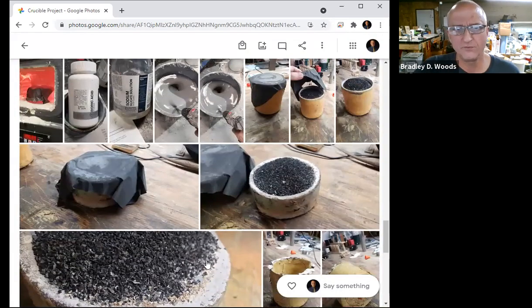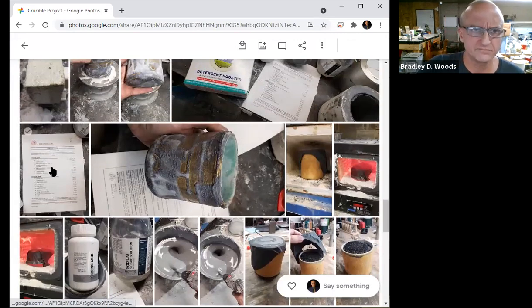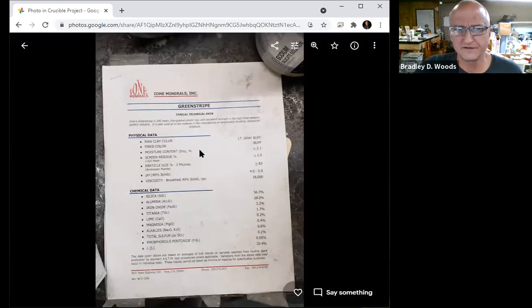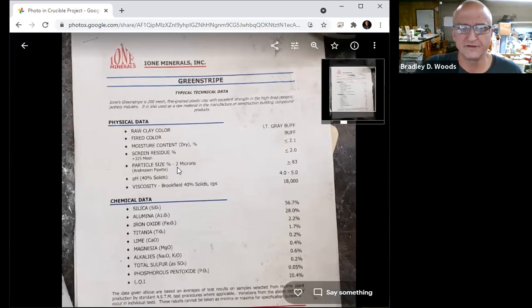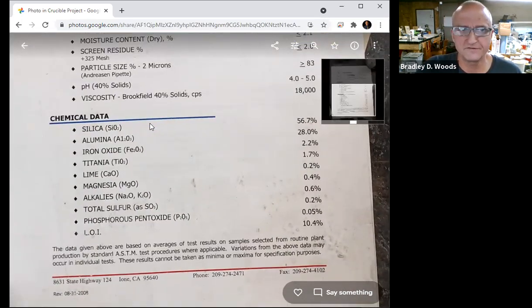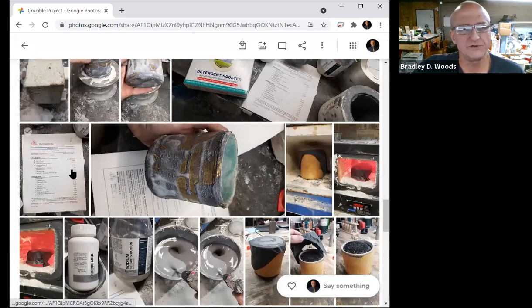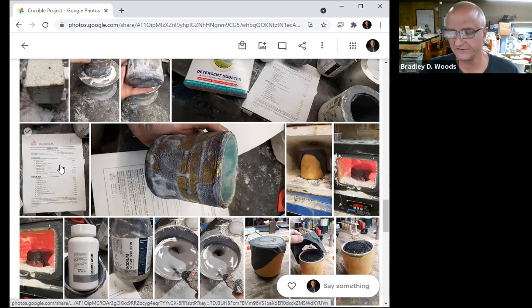So that was when I switched, and we're going to share the recipe publicly. This is the technical data for the green stripe clay. And you can see it's simple. It's mostly silica, some alumina, and a bit of iron oxide. To that, we use 80% of the green stripe clay by mass, and then we add 20% powdered Pyrex, so powdered borosilicate. And this stuff's easy to come by online. It's just recycled lab glass and things like that, and it's used for a lot of different industrial purposes. So it can be had for just a few dollars a pound.